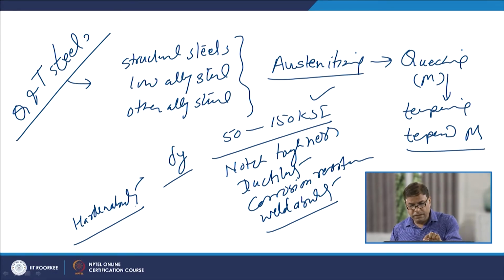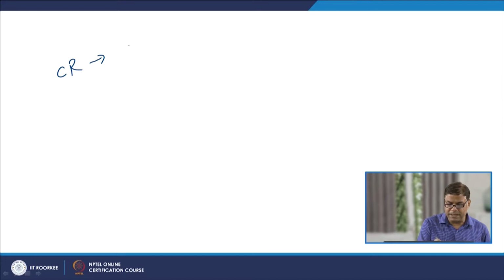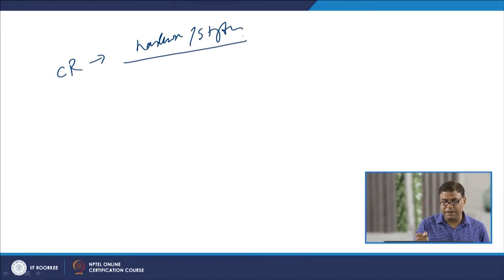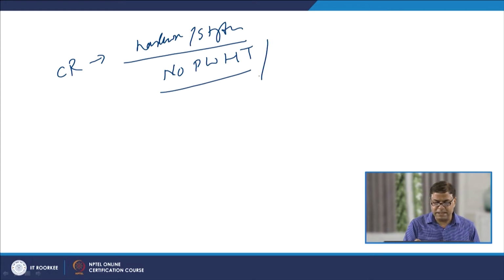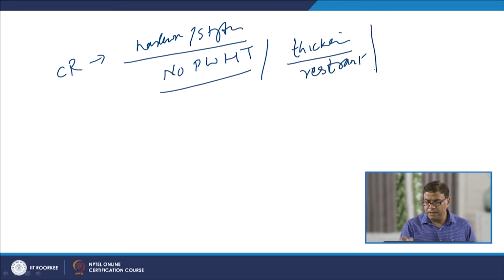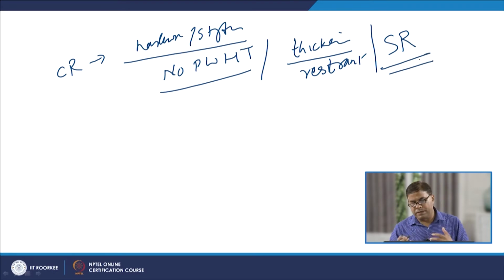So, whenever these steels are welded, generally fusion welding offers the cooling rates which result in reasonably good hardness and strength of the weldment, and that is why generally no post weld heat treatment after the welding is needed with these steels, except when very thick sections are being welded and the welding is being carried out under the restraint conditions. In those cases, the stress relieving heat treatment is carried out, so that whatever residual stresses are being developed can be taken care of.